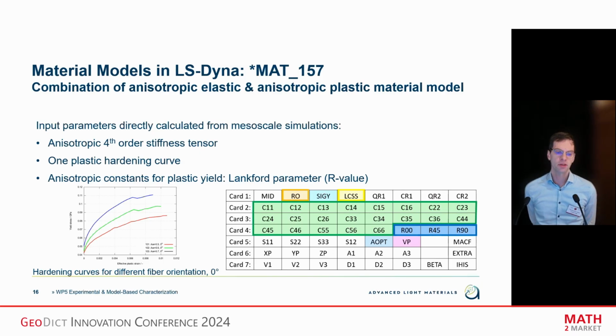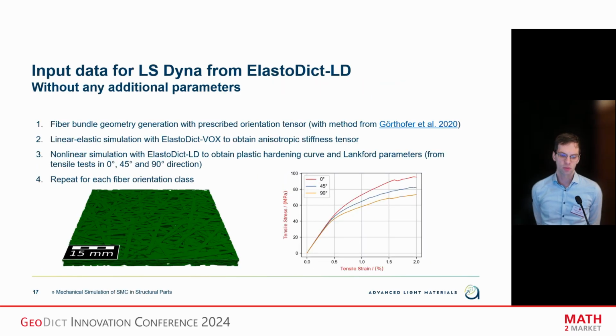We chose a material law, MAT 157, which is quite common for fiber reinforced composites, which is a combination of an anisotropic elastic and anisotropic plastic material model. As input for this material card, you need an anisotropic stiffness tensor, a plastic hardening curve, and then you need Lankford parameters or Hill parameters, depending on the element type which you use in your finite element simulation. And luckily, all these parameters you can obtain from these mesoscale simulations.